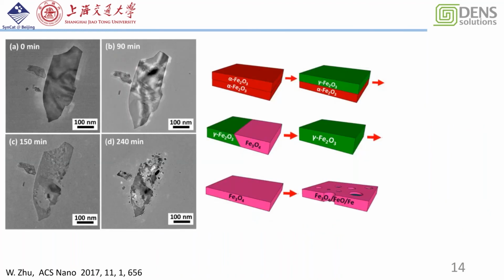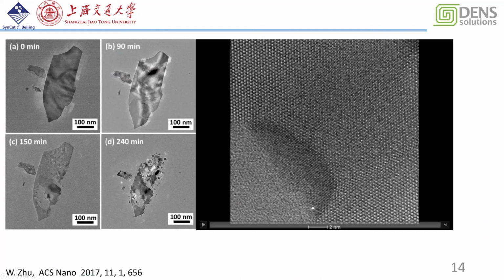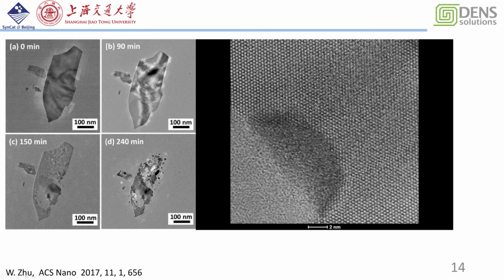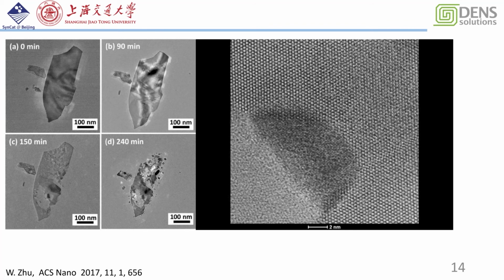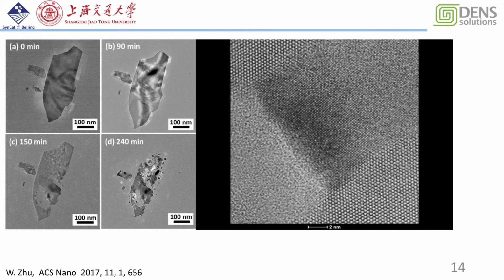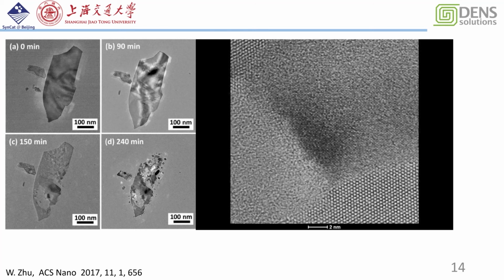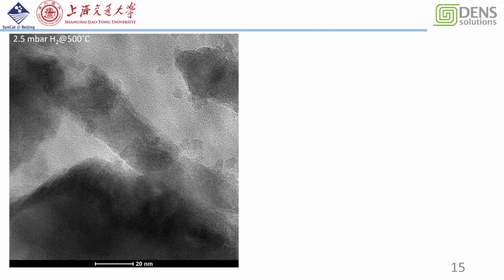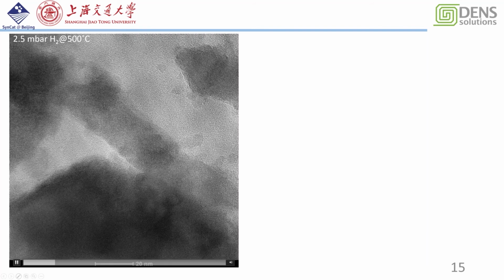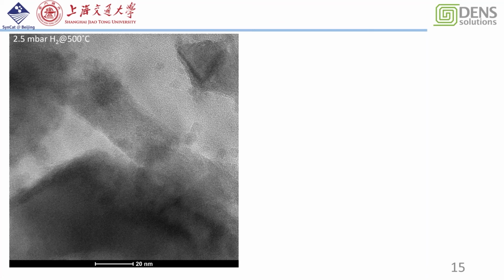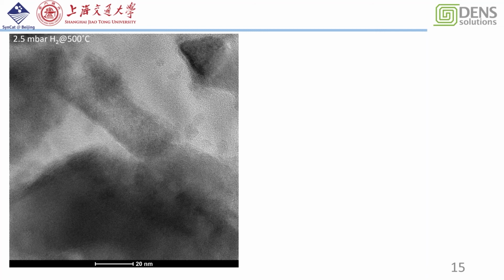This work, published in 2017, got very beautiful images of how this topochemical transition from the hematite to magnetite happens. They used a very low pressure, 0.2 Pascal of hydrogen, in the TEM to visualize this process. And in my experiment, I reproduce this result, but use 2.5 millibar, almost 1,000 times higher than this one, at 500 degrees for the reduction process. So it looks like this process is very different from the paper published in 2017.